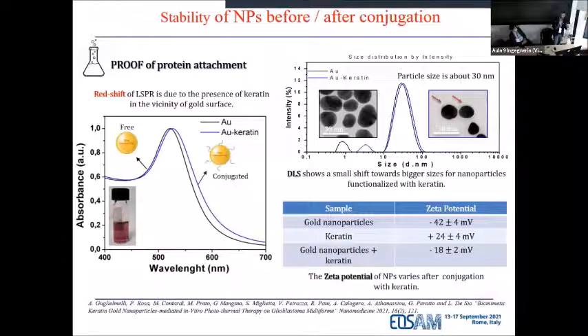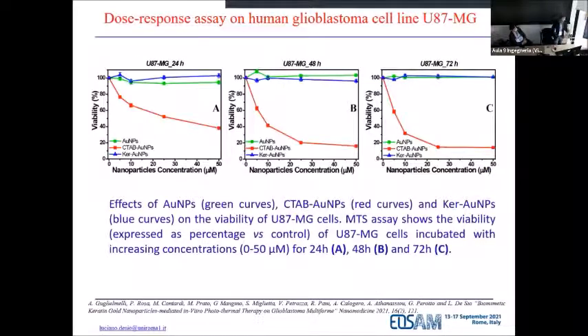So once we were sure, even with other techniques, that we have stable keratin-coated golden nanoparticles, we decided to check now the viability of those particles. And as a comparison, we have here CTAB-capped golden nanoparticles and also citrate-capped golden nanoparticles, like the ones you can buy very easily. So to give you an idea, the red curve is the viability in the presence of golden nanoparticles with CTAB. And you can see that after 24 hours, due to the very high toxicity, you can easily kill the cells. And this is something bad, because we don't want to kill the cells with the toxicity of the material. We want to kill with an external perturbation like light. Conversely, you can see that for our particle, the blue curve, the viability is very high, 100% I should say, even after 72 hours of incubation.